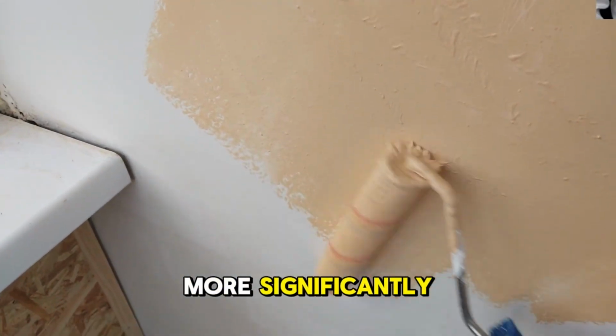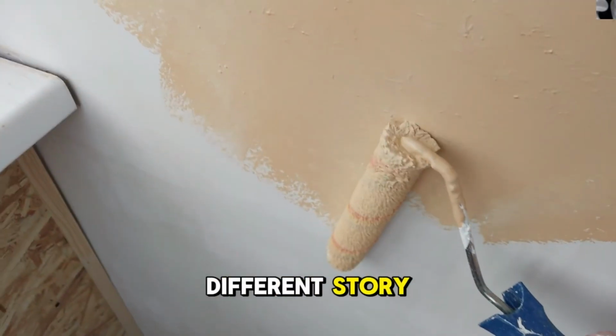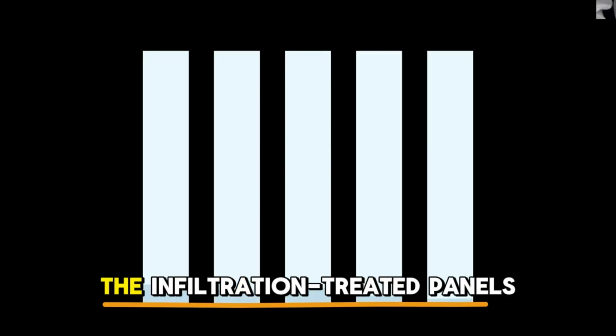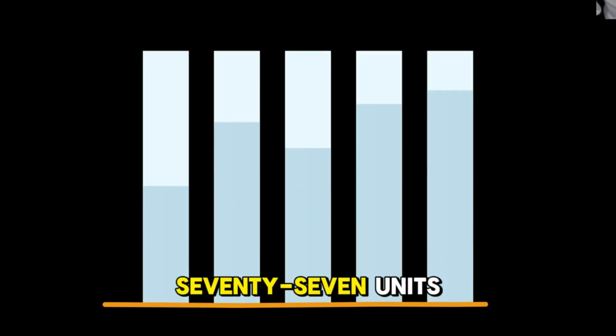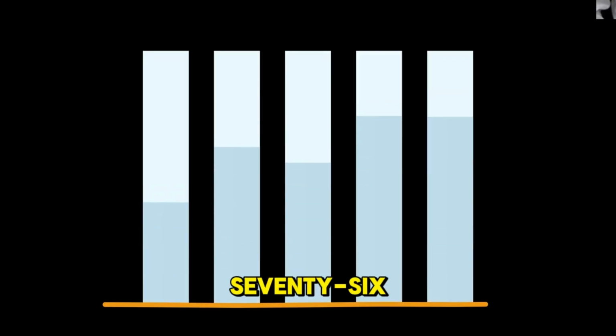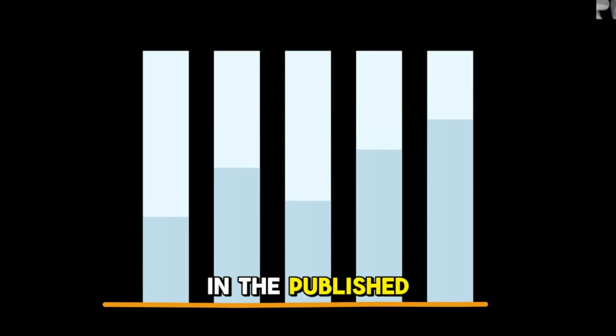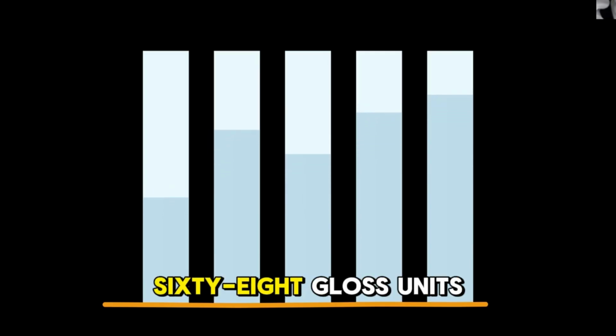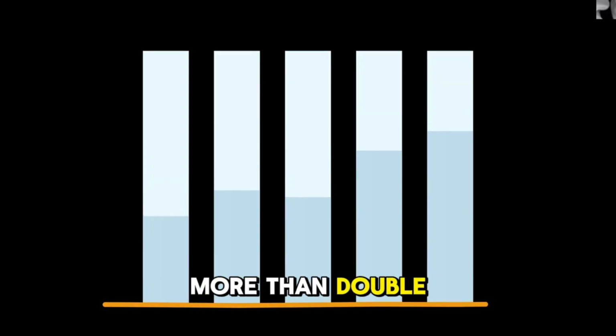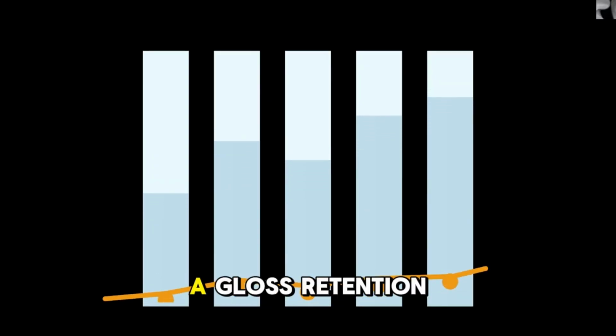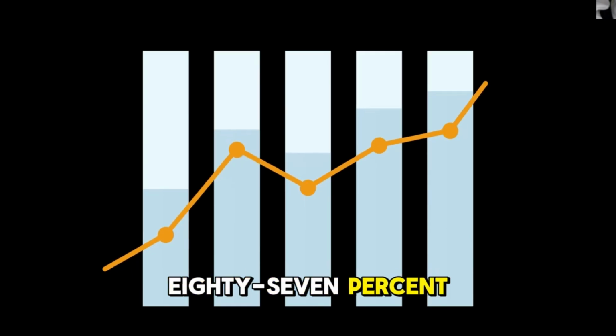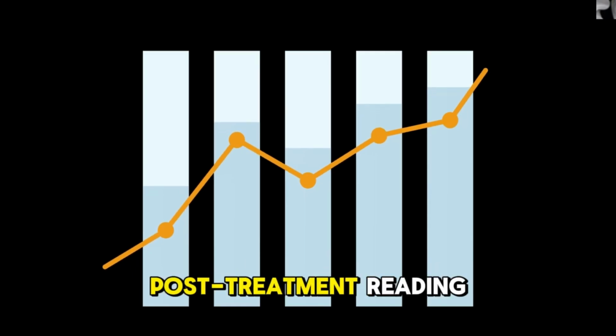More significantly, the follow-up measurement schedule told a different story from the wax panels. At 4 weeks, the infiltration-treated panels measured 77 units. At 12 weeks, 76. At 6 months, 74. At 18 months, 71. At the final measurement point recorded in the published study, 36 months after the single treatment application, the panels averaged 68 gloss units, more than double their pre-treatment condition, and representing a gloss retention figure of 87% relative to the immediately post-treatment reading.